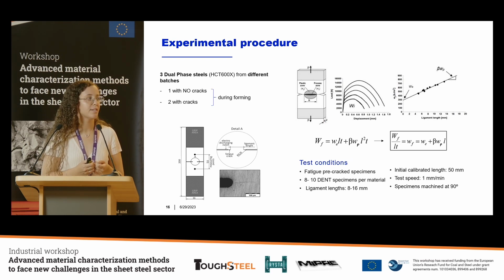And then we need to do it for different ligament lengths to separate these 2 energetic contributions. And when we perform all these different tests for the ligament length, we can scale this work of fracture and make a regression, which you can see in the slide. The intercept of this regression is the essential work of fracture value, which is this interesting result for cracking resistance. And also we can get the slope, which is the non-essential plastic work.